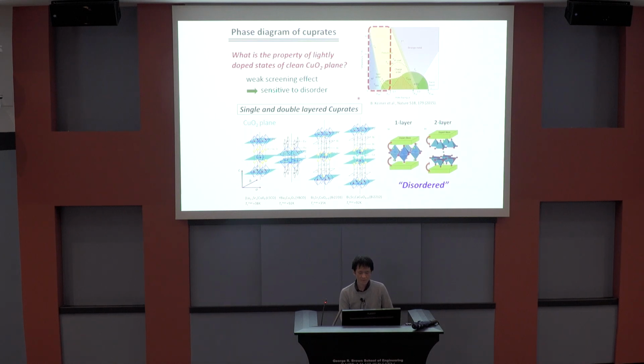Especially the lightly doped state is very sensitive to disorder because of the weak screening effect. And this phase diagram is mostly constructed based on the study of single and double layer cuprate, which has disorder.